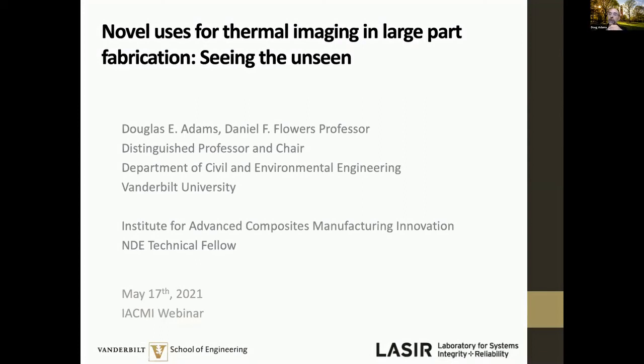So in some ways, using thermography during the process to look for flaws that are forming is similar to what we do after the process using techniques like CT scan or ultrasound. But in some ways it's different, because what you're looking at is the material evolving, and you're tracking that evolution. If the properties don't develop the way you would like as the process engineer, you can potentially spot that as well. So even if it's not a void, it might be a material that you're not happy with, and you can identify that by virtue of the fact that the process didn't go the way it was supposed to. Hopefully that answers your question.